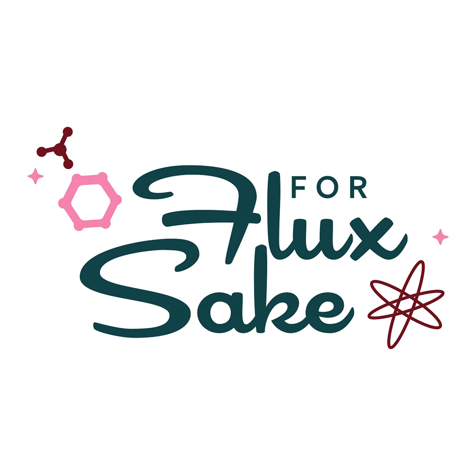But the short version is, for Teresa, you're fine. Go with the 7.5, and hopefully all the glazes are working for you. They should be okay at that extra 1 cone higher. But again, we're not firing to a temperature. We're firing to the completion of a chemical reaction. So it'll probably be okay.